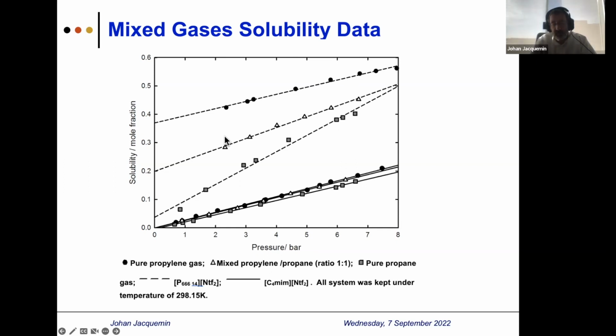So it's a single gas solubility. And if you look at the open triangle, it's with a mixed feed with a mole ratio of 1:1, basically. And one can see from this that the distribution or separation factor cannot be simply obtained from the single gas solubility in ionic liquid, just to echo, or in porous liquid, just to echo published papers